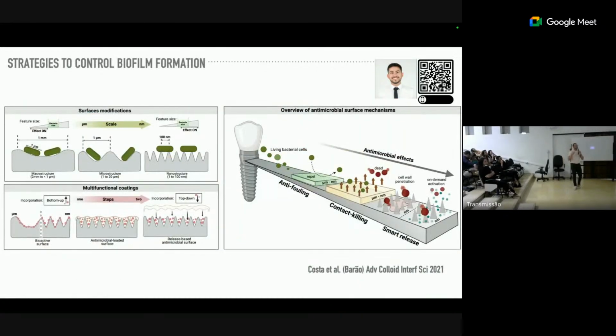If you talk a little bit about the mechanism of how the surface of dental implants can control this biofilm formation. As you may see here, we have a surface with macro, micro, and nano structure. It's very tricky for us between Portuguese and English, because this is micro in Portuguese and English is very difficult. So this is the size of the bacteria, 1 micrometer, for example. If you have a macro structure, we're going to have a very long way so that bacteria can adhere on the surface. If you have a micro, we're going to reduce.